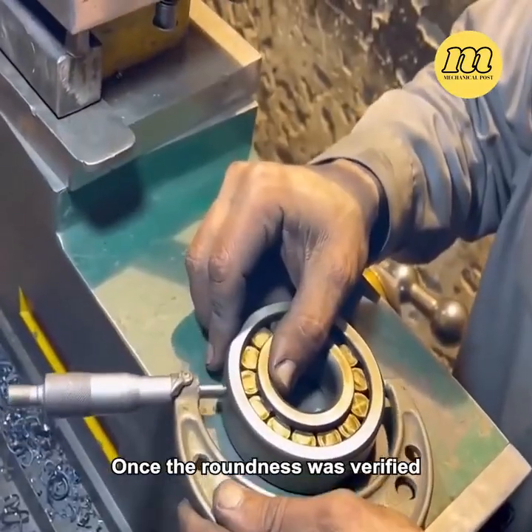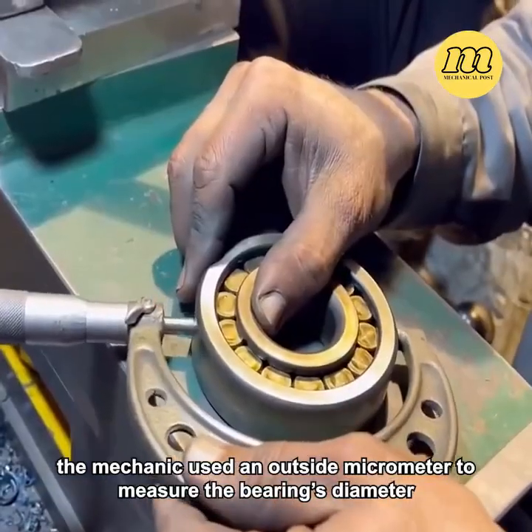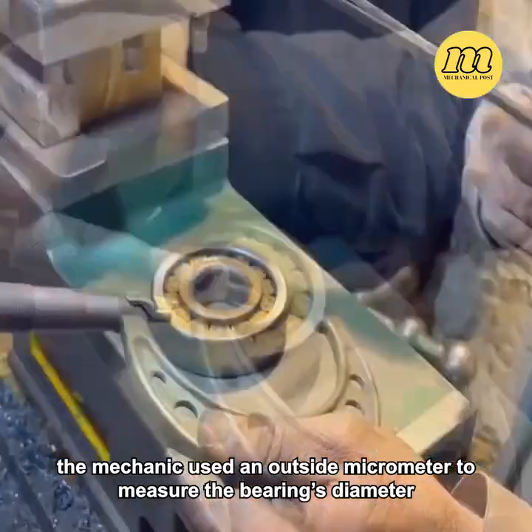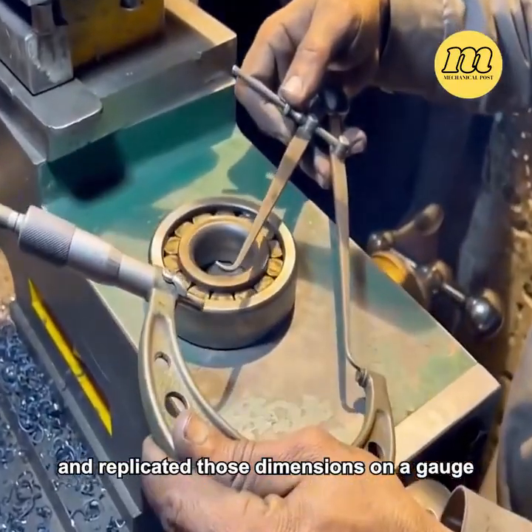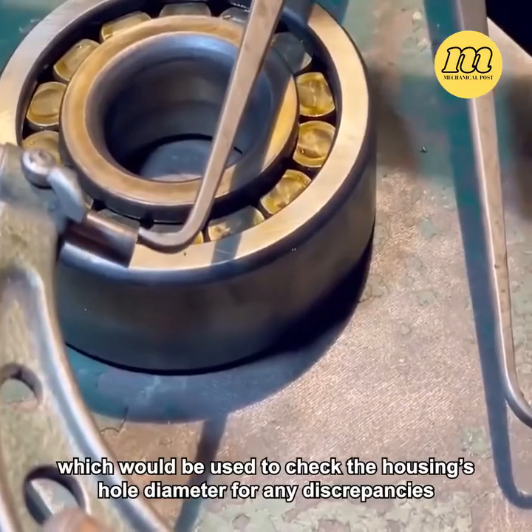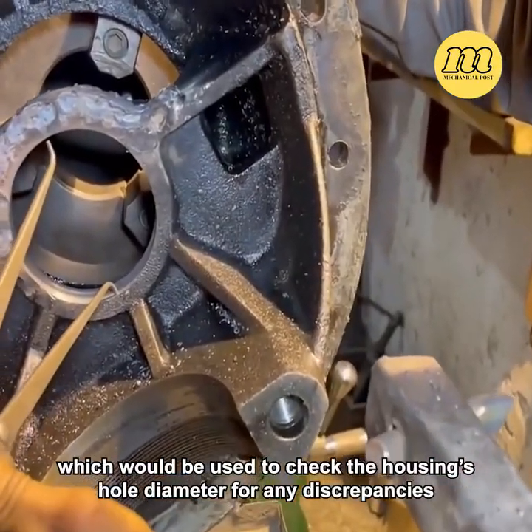Once the roundness was verified, the mechanic used an outside micrometer to measure the bearing's diameter and replicated those dimensions on a gauge, which would be used to check the housing's hole diameter for any discrepancies. After confirming there were no errors, the mechanic used a welding rod to add more material to the inner wall. This process reduced the hole's diameter and increased the strength of the welded bearing retaining ring.